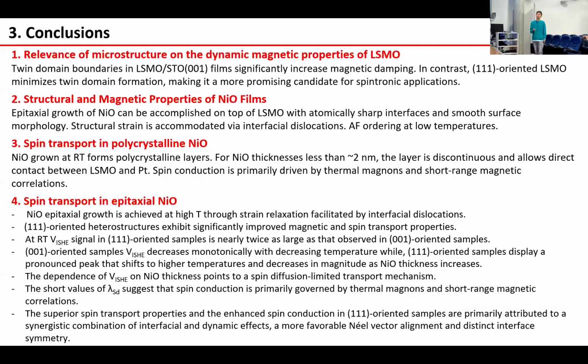So finally, I will introduce my conclusions. First, we studied the relevance of microstructure to the dynamic magnetic properties of LSMO, and found that the twin domain boundaries in the LSMO STO 001 film significantly increase magnetic damping. In contrast, the 111 oriented LSMO minimizes twin domain formation, making it a more promising candidate for spintronic applications.